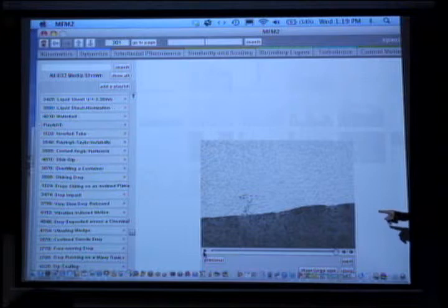Okay, and so it's kind of interesting. In order to kill the contact angle hysteresis, and we'll see why you might want to do that in a moment, you want to make the surface either really smooth, so you have no such heterogeneities, or you want to make it really rough. So there are two ways to go. If you put two drops on a real surface, you will observe them at different angles.